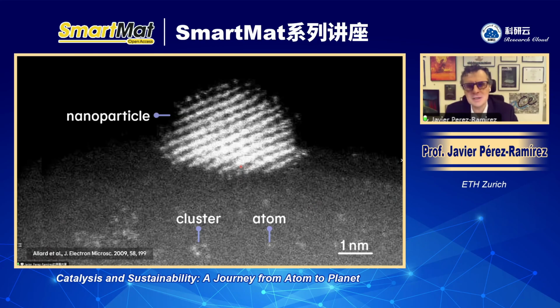And so I want to illustrate this because in heterogeneous catalysis, very often we create these kind of architectures where typically you can see here nanoparticles. These are supported nanoparticles. This is a gold nanoparticle. This is an example I took from this publication in 2009. But if you look more carefully with a microscope, you can see that in addition to these beautiful and bright gold nanoparticles, the catalyst also contains some dirt.